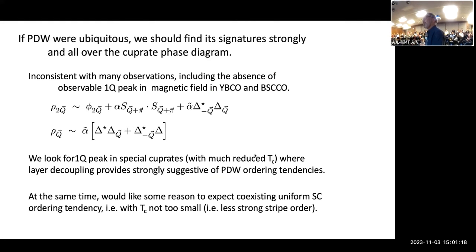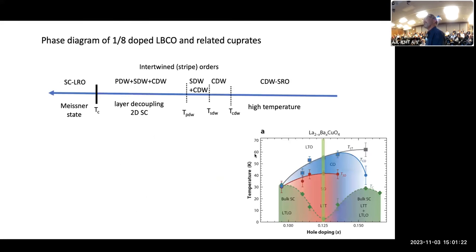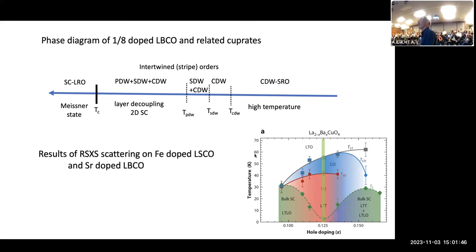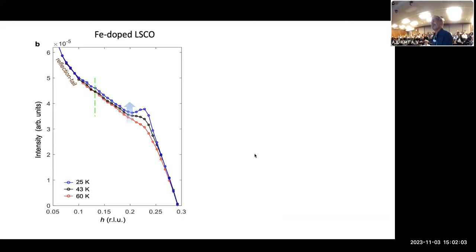So I'm now pressed on time, but let me now return to this material. Let's look both just below here where we think we have pair density wave and as close as we can get down to here where maybe we have both pair density wave and uniform superconductivity, and see if we can find a 1Q peak. And this is done with resonant X-ray scattering, resonant elastic X-ray scattering on two particular cuprates in this family. And now, okay, so here's the actual data.